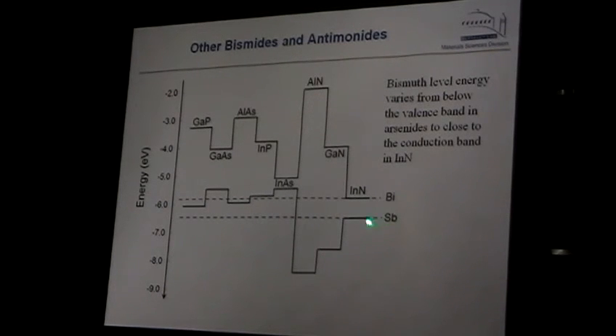We know where the antimony level is. We know where the bismuth level is. Now we know how the conduction band edge goes for different materials, and the valence band edge. So if you take antimony and put it in gallium phosphide, you would have something which is isolated above the valence band edge, right? In gallium arsenide, we know it is below. Again, antimony is everywhere below, except aluminum nitride and gallium nitride. So in this case, we could, in fact, form the localized level very well above the valence band edge. And this would be interesting.